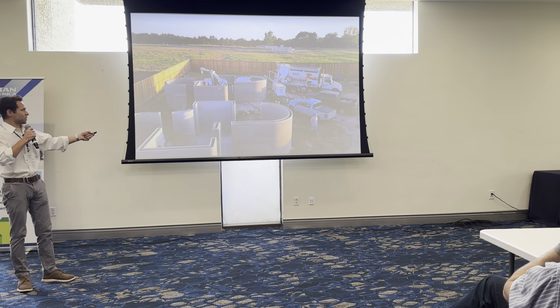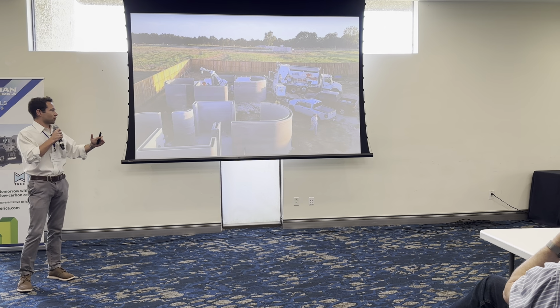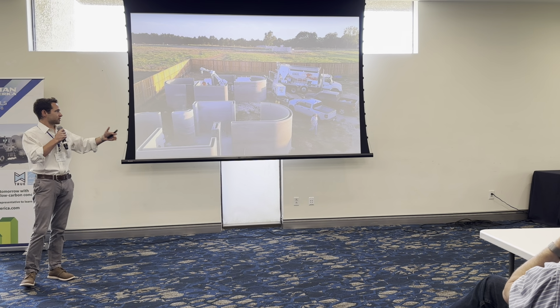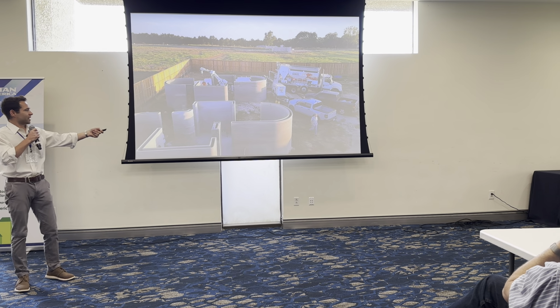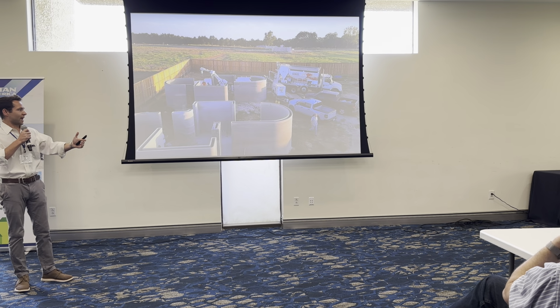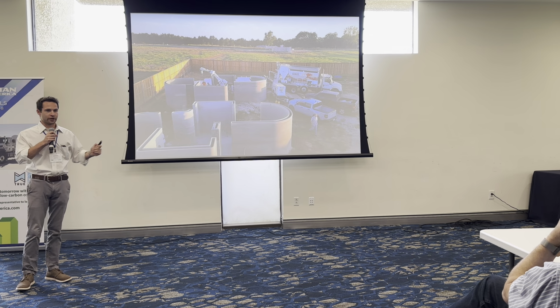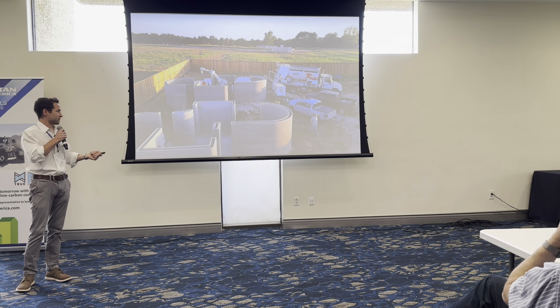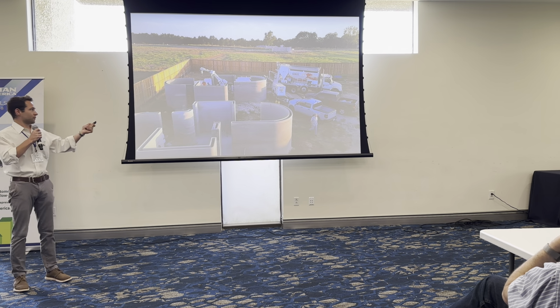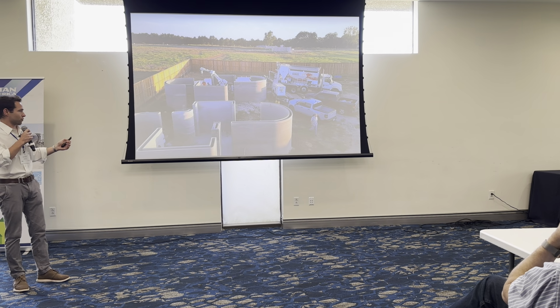They were able to do this by implementing this grout truck, which is almost like a batch plant mixer on site. They put the raw ingredients into the truck, and it gets fed into a mixing system rather than shoveling it in by hand. This allowed them to almost double their utility of their printing daily. So it went from printing a house in 6 or 7 days to being able to achieve these small, tiny homes in maybe 3 or 4 days.